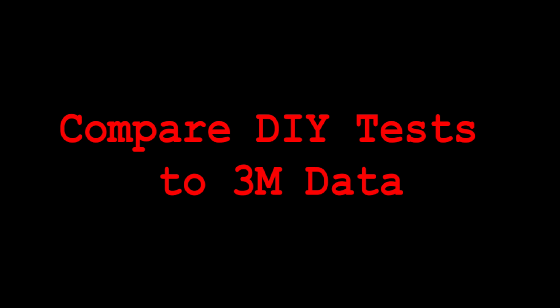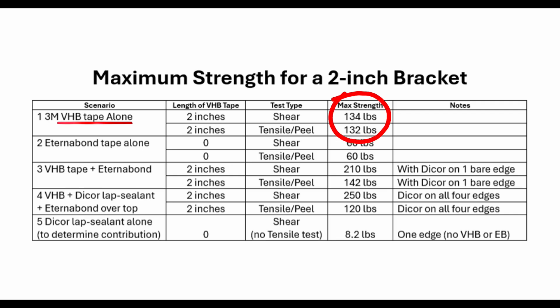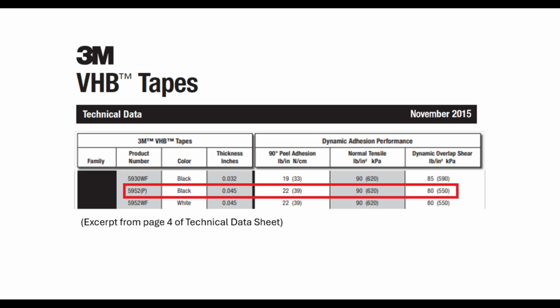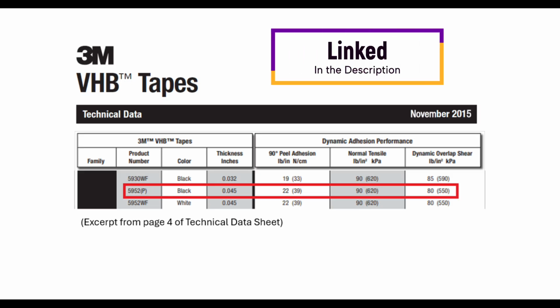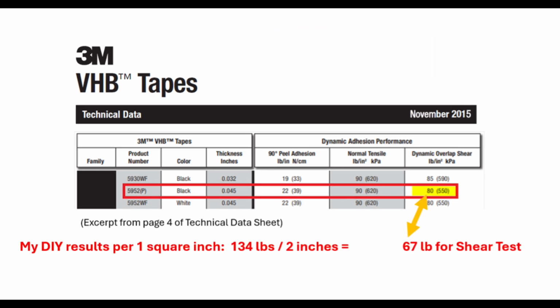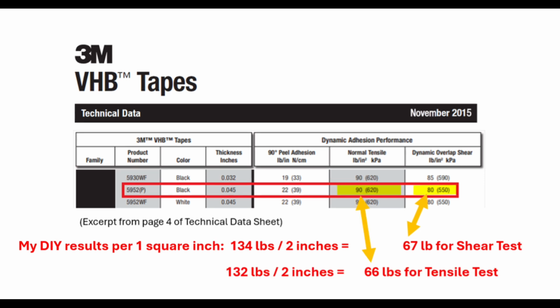Now let's compare our VHB numbers to 3M data from their November 2015 technical data sheet for VHB tape number 5952. Their results are per square inch, and mine are for 2-inch pieces of tape. So if I divide mine by 2, I get 67 pounds per square inch for the shear test in comparison to 3M's value of 80 pounds per square inch. So mine is 16% lower, and my tensile test is 27% lower.